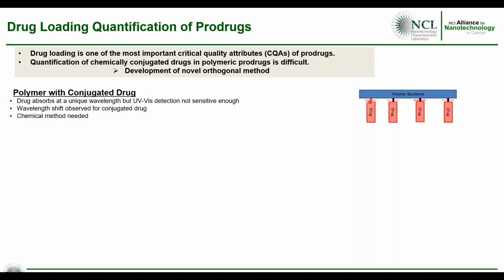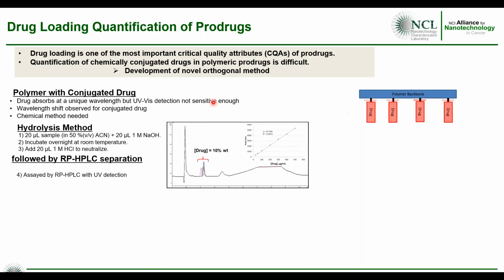So traditionally what you do is you want to do some kind of hydrolysis method for this, because typically these drugs, when you conjugate to the polymer backbone, you might shift the optical properties or spectral properties of the drug, so you can't use UV vis anymore. Plus, typically these drugs are loaded at such a low amount that UV vis detection is just not sensitive enough. So we need to come up with a chemical method, and hydrolysis method, like I mentioned, is the easiest, whereby you simply just incubate your sample in either acid or base, let it cleave, and then develop a reverse phase HPLC method to look at the free drug.